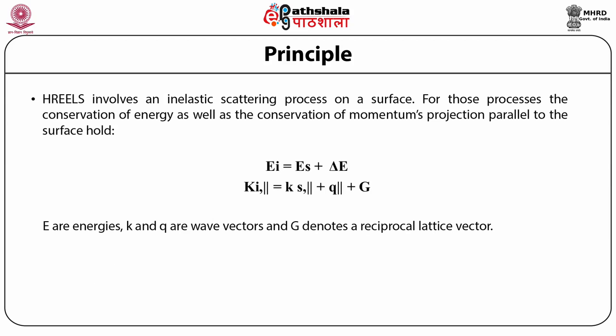HREELS involves an inelastic scattering process on a surface. For those processes, the conservation of energy as well as the conservation of momentum's projection parallel to the surface hold, and is given by a mathematical relation, that is EI, the incident energy, is equal to ES plus delta E, and KI parallel is equal to KS parallel plus Q parallel plus G. E are energies, K and Q are wave vectors, and G denotes a reciprocal lattice vector.